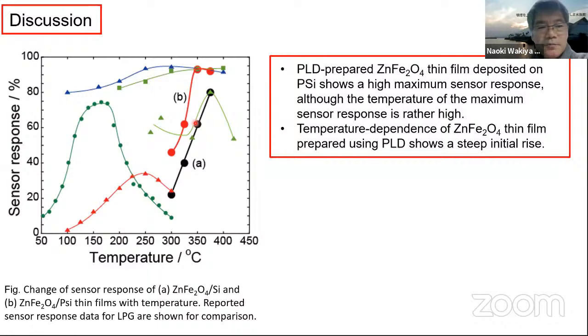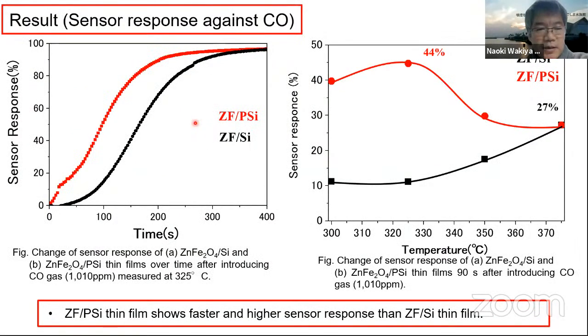And in the case of the CO gas, this is the zinc ferrite on silicon and on porous silicon. The zinc ferrite thin film on porous silicon shows a high sensor response and quick response. And this is the temperature dependence of sensor response. So this slide shows that the zinc ferrite thin film deposited on porous silicon shows a faster and higher sensor response than the zinc ferrite thin film on silicon.